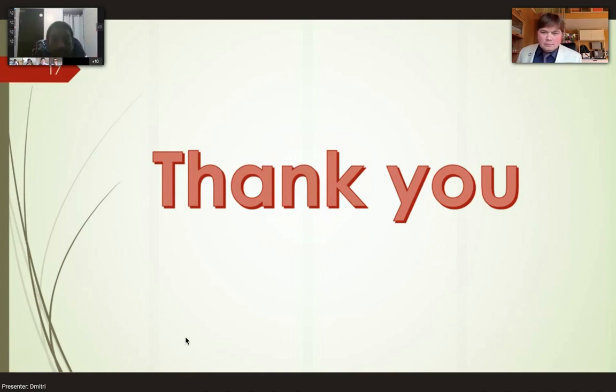So it's a nice work. You are very brave. It's a good exercise for the course. Now, if you are thinking about it from the research side, there are lots of issues that you should pay attention to. The first one is that the band gap you calculated is significantly lower than the actual band gap. The band gap of LLZO is about 6 electron volts. Yes. And the largest value you got is about 4 or something.